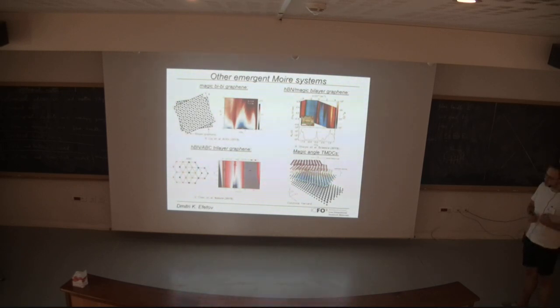We have now also a study coming up about the second magic angle, which is around 0.5 degrees, and we can say that we really see flat bands, many flat bands actually arising at the second magic angle. Most groups in magic angle graphene concentrated, however, on the 1.1 degrees. Because there's still a big uncertainty in device fabrication, you end up with a huge variety of different angles at the end of the day.